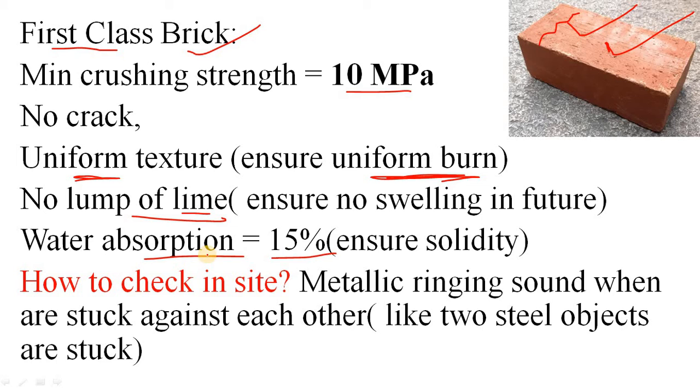Next point: water absorption should not be more than 15%. What does this mean? Water absorption happens in bricks due to capillary action. So if there are more cavities, more capillaries, more interconnected pores, obviously the water absorption will be more. And if porosity is more, obviously its strength will be less. So to ensure solidity, we ensure that water absorption is less than 15%.